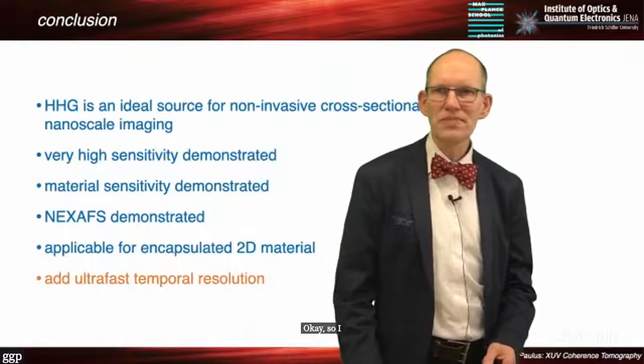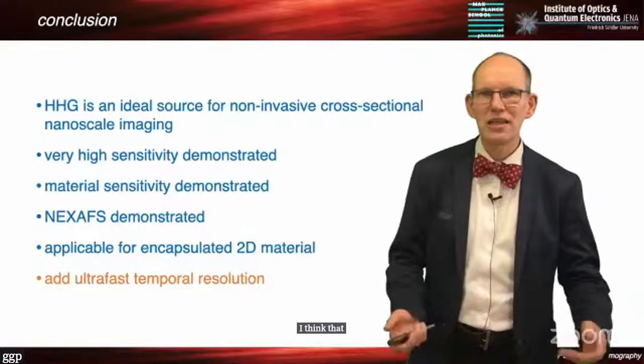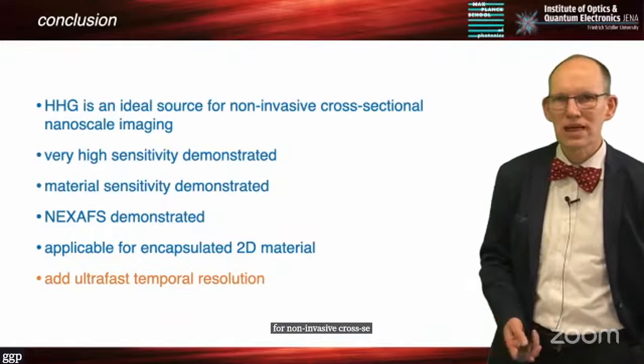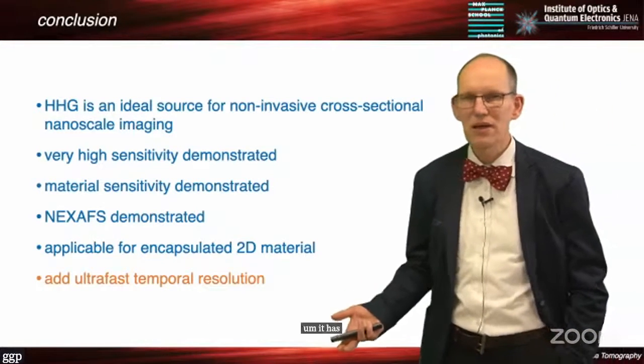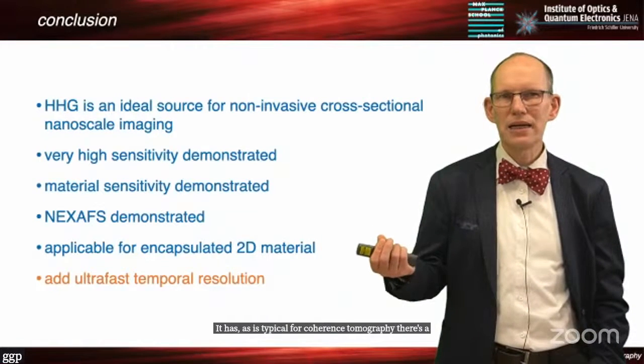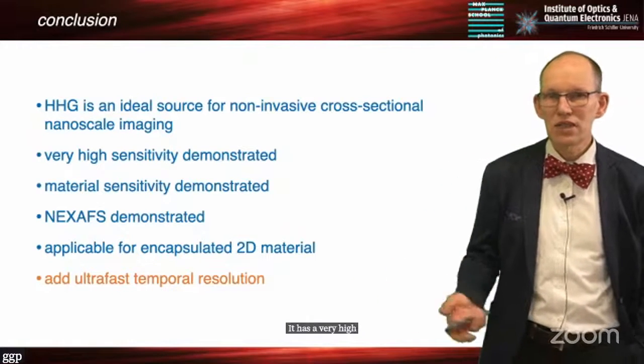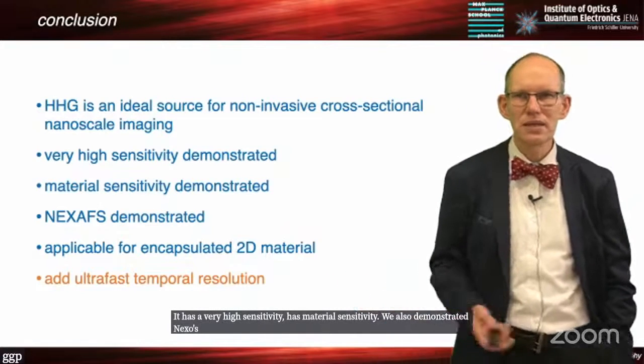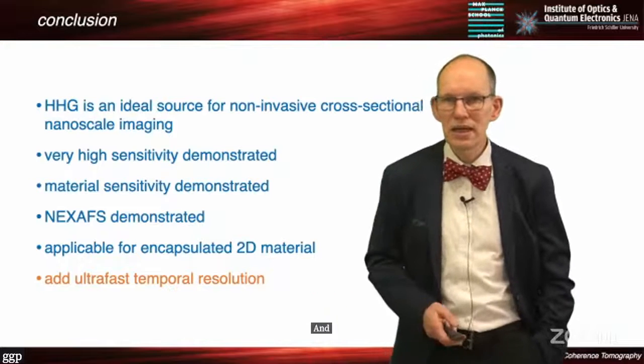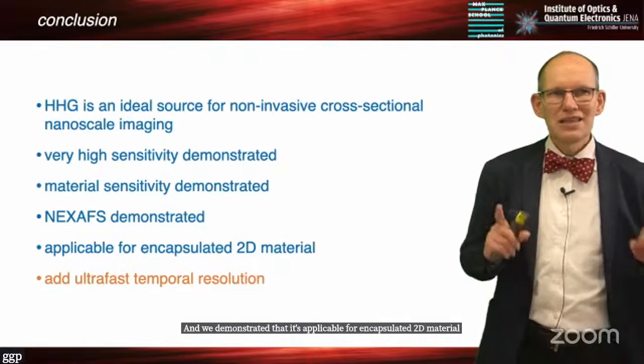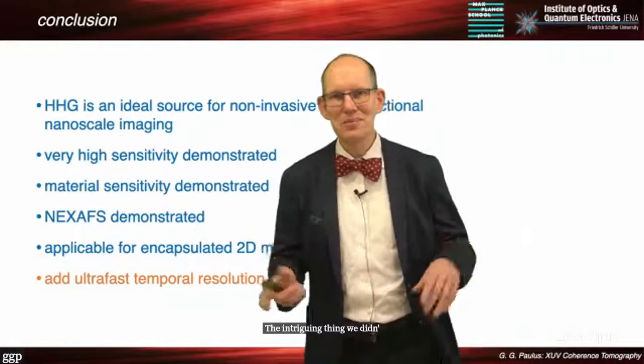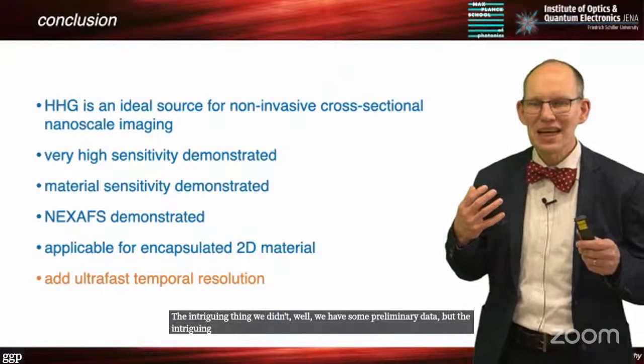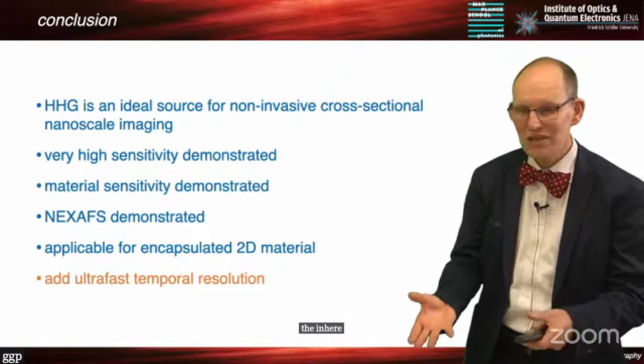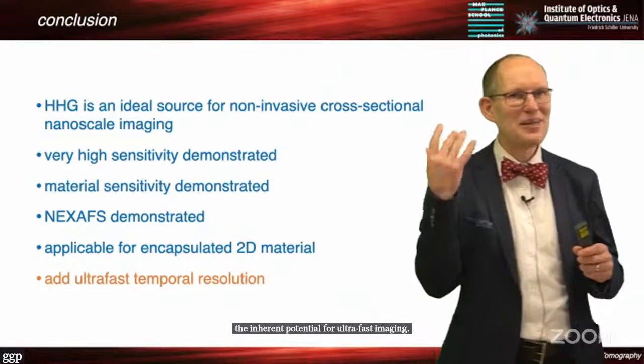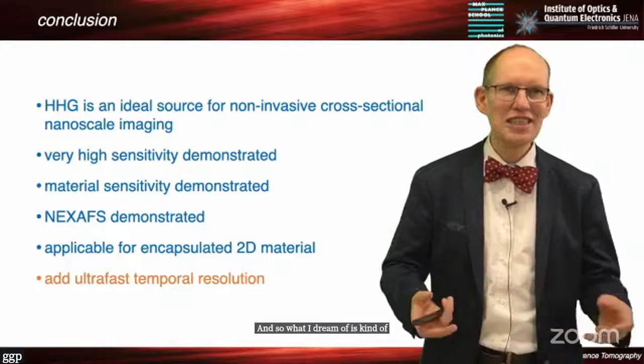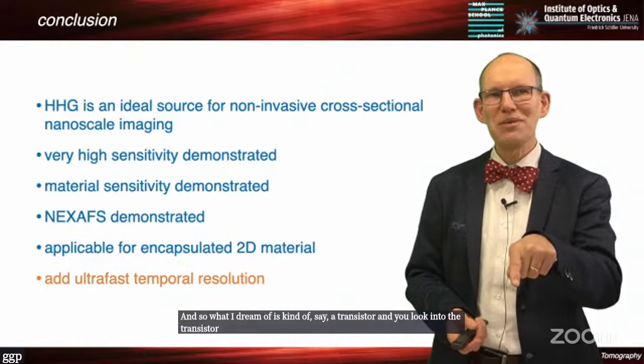Okay, so I come to the conclusion. I think that high harmonic generation is an ideal source for non-invasive cross-sectional and nanoscale imaging. As is typical for coherence tomography, it's a white light interferometric method. It has a very high sensitivity, has material sensitivity. We also demonstrated NEXAFS, has little to do with imaging. And we demonstrated that it's applicable for encapsulated 2D material. The intriguing thing, we have some preliminary data, but the intriguing thing is, of course, the inherent potential for ultrafast imaging. What I dream of is, say, a transistor, and you look into the transistor and watch the time-dependent current.